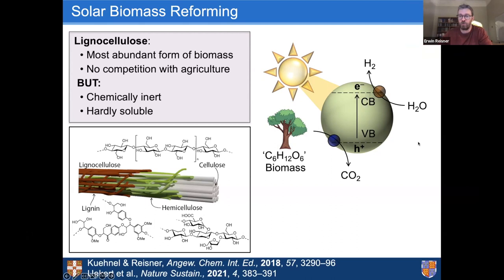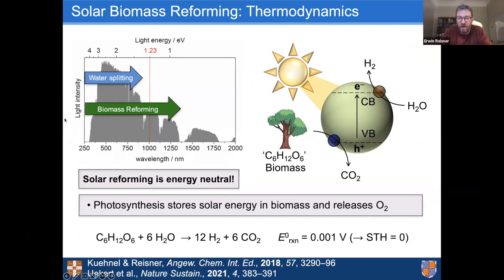So what is another aspect that's really attractive about biomass reforming compared to water splitting or water oxidation? It really is the thermodynamic requirement. I mentioned before that water oxidation is challenging. And if we couple water oxidation to proton reduction, we have quite a positive Gibbs free energy. It turns out if we replace the water with biomass, or let's say as a model, glucose oxidation, we are almost thermoneutral. So the Gibbs free energy is close to zero. And this is simply because our substrate already contains a lot of energy. All we are doing in the photochemical reaction is unlocking the energy from the glucose and simply putting it into the hydrogen.